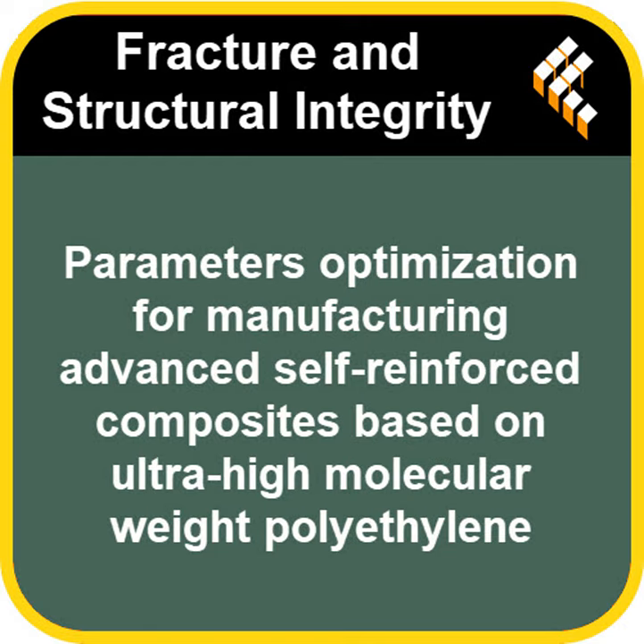What about bending? How did it hold up when bent? Bending strength and also the stiffness or elastic modulus in bending showed a really interesting pattern. It wasn't linear. How so? They both increased with temperature at first, hit a peak value, and then dropped off quite sharply at the higher temperatures. Similar peak temperature range? Pretty much, yeah. Maximum bending strength was around 130 MPa, and the maximum stiffness around 42 gigapascals, GPa. Again, happening in that 165, 170 C sweet spot for the lower pressure.